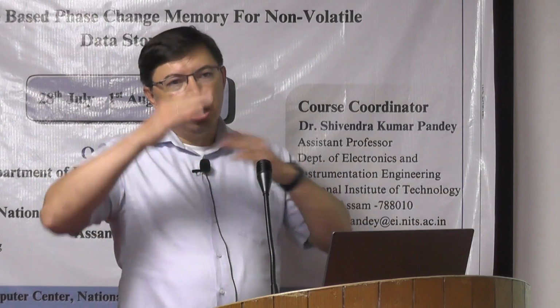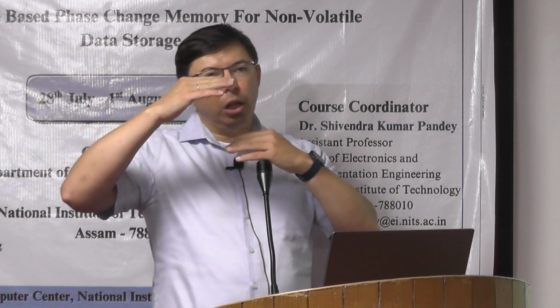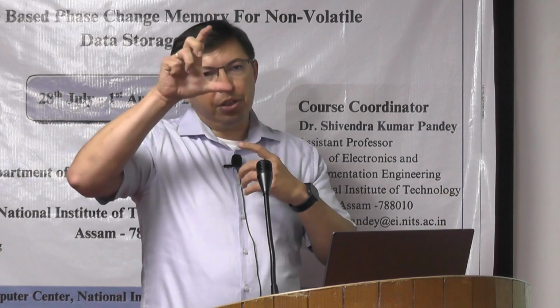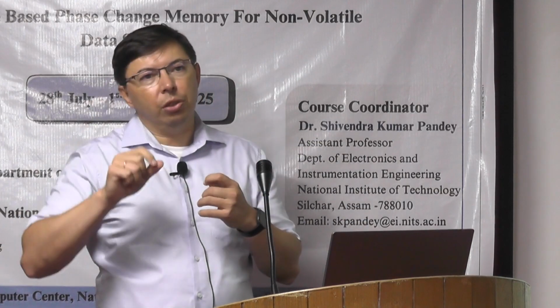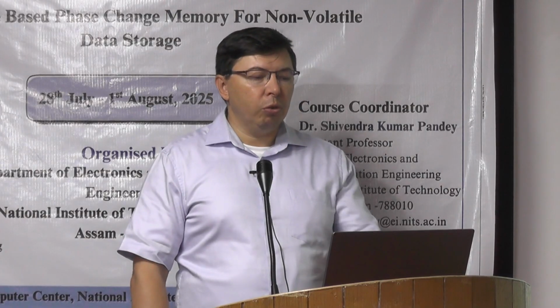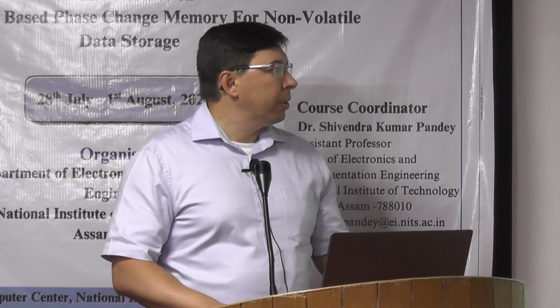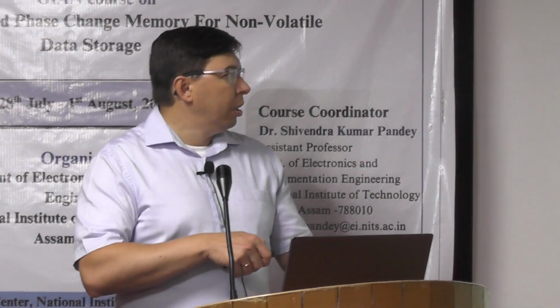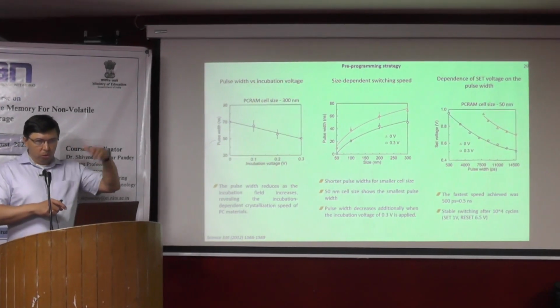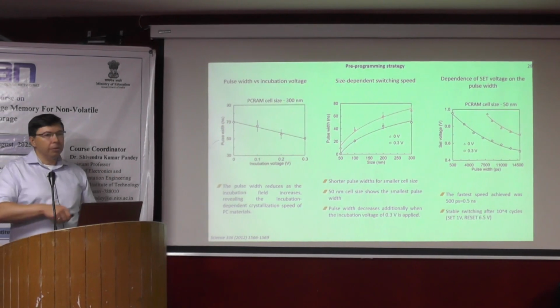But it's still enough. The resistance contrast, as you know, is 2 orders of magnitude. This is a large window, GST has a very large window. So it's enough to read the information. Of course, you should select this incubation voltage very carefully. Should not go to more than this.